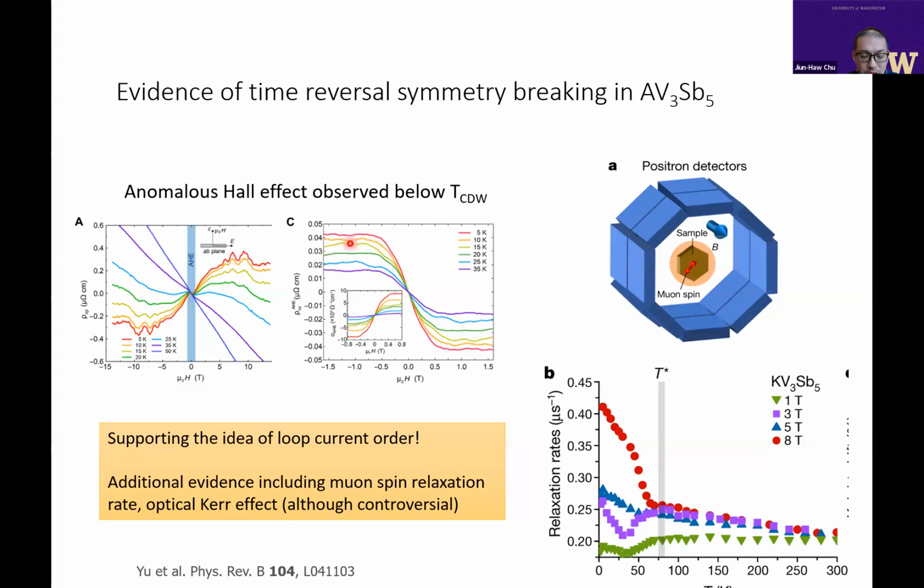And then you might argue that nonlinear Hall is not that unusual. You'll see nonlinear Hall in a two-band system with electron and hole carriers, which will give you two different slopes at high field and low field. But notice that in these very low temperature measurements, you already see some nonlinearity at a much higher field scale, which is superimposed on this low field nonlinearity. To generate this kind of nonlinearity, you need at least 4 bands with very different mobility. Which is not totally impossible, but this also makes the anomalous Hall effect more convincing compared to the nonlinear Hall coming from a two-band model.